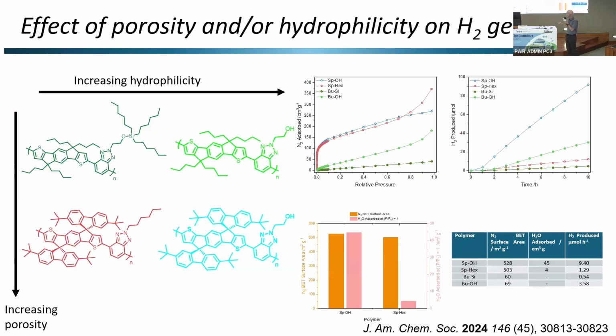I think I have a couple of slides left just to say that you don't need to have a COF to generate internal porosity. You can use simple spirocyclic techniques to get what we call polymers of intrinsic microporosity. They also have high internal volume. So we played around with a bunch of these. The take-home message here is, yes, if you have this internal porosity, you can drive a more efficient photocatalytic process. But the key really is not the porosity. The key is the hydrophilicity. If you want to bring water into your nanoparticle to do the chemistry, it's not enough just to have a pore. It has to be a hydrophilic pore. So this material has both high internal porosity and hydrophilicity, and this has by far the highest hydrogen evolution rate.